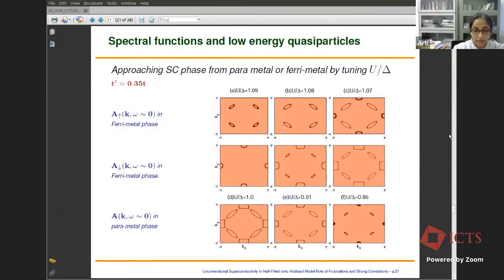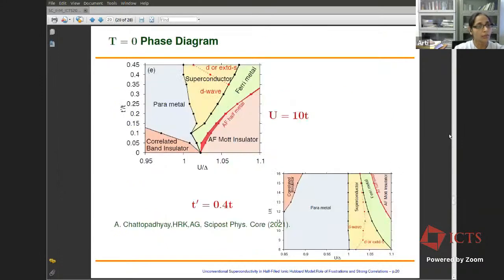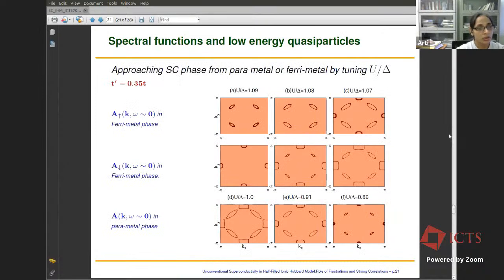Now, to understand why the system has to go via a metallic phase to become a superconductor, we look at the low energy spectral functions of various metallic phases. So here I'm showing you the low energy spectral function for the up and down spin. The top layer is the up spin and the bottom layer is the down spin. And you can think of it as moving, say, from the ferri metal to the D wave superconductor. So when you start from the ferri metal at large U by delta, you see that the spectral function shows these small Fermi pockets. These are the electron pockets actually.